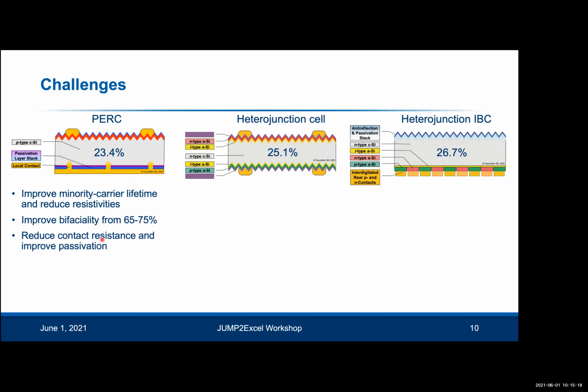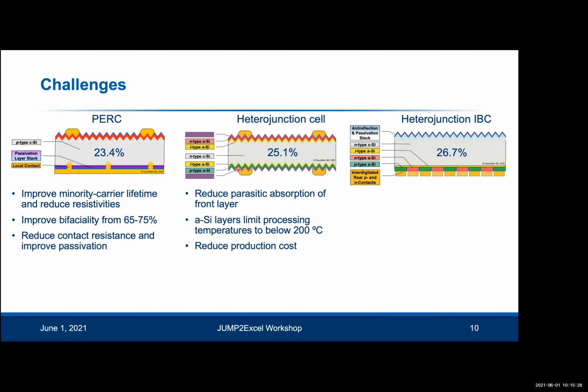This also needs to further reduce the contact resistance at these local contacts, as well as develop better passivation methods. For the heterojunction cell, as I mentioned, it's limited by parasitic absorption from the front layer. And usually there's also transparent conducting oxide deposited on top to reduce the series resistance.